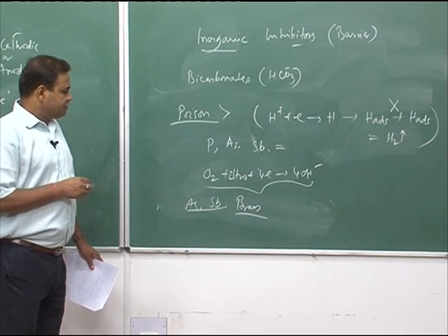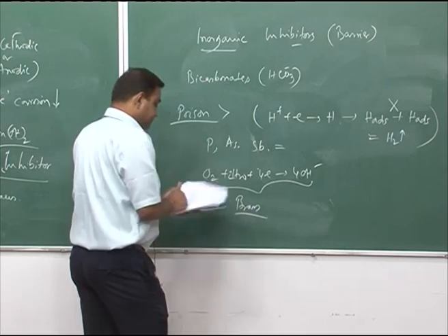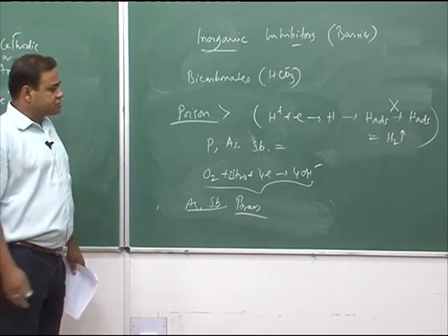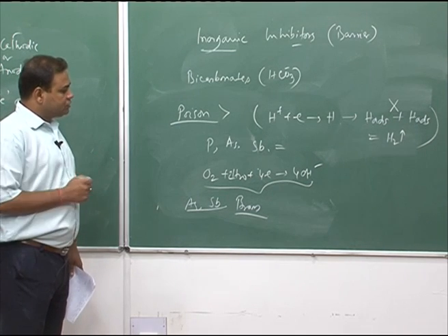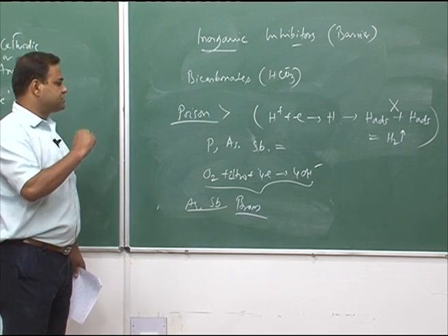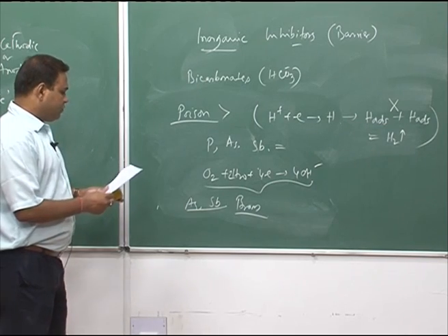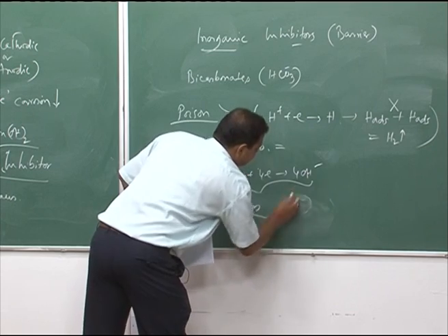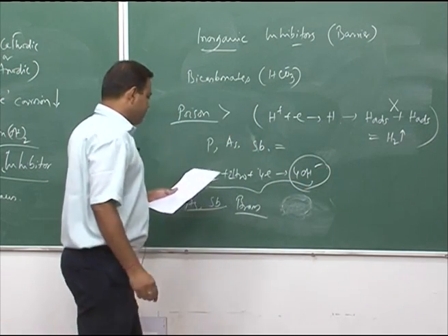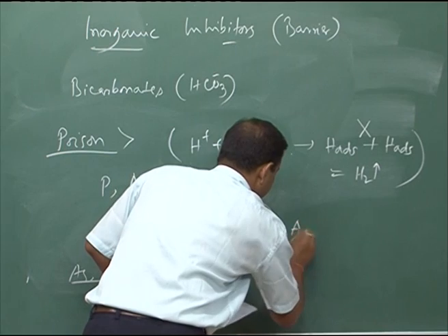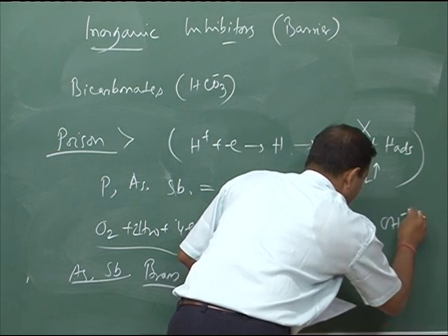The mechanism is that during corrosion, initially the copper as well as the zinc go out, both ions go out, and then copper redeposits back. Now the copper would react with arsenic, and it can form an arsenic hydroxide phase.